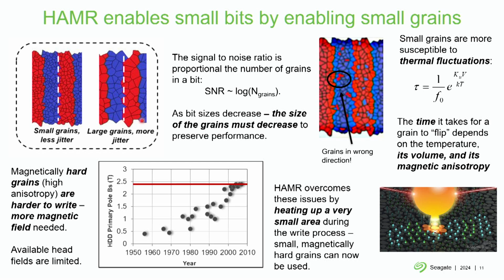So one way to maintain the stability or increase it is to increase the magnetic anisotropy, which is just a measure of the magnetic hardness. And there are materials that have high anisotropy, but they're difficult to write if I just have a magnetic writer. And there is a limit to the magnetization that's available in the materials that we know of. And especially as we try to decrease the size of the writer, as we're trying to decrease the size of the bit, that available field decreases significantly. So we can't just increase the anisotropy.